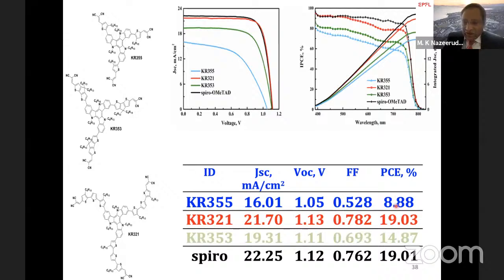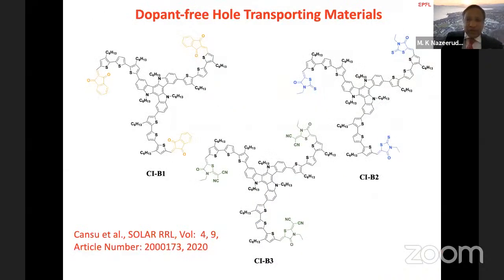With one thiophene, the efficiency is not very high. With two thiophenes, the efficiency without any dopants is around 15%. With three thiophenes, there's KR321, the red entry, with around 19% efficiency. This is a pristine molecule, synthesized and directly absorbed onto the surface. On the contrary, the spiro is with the dopants, and the efficiencies are comparable. So here we have a huge success in demonstrating dopant-free hole transport materials as efficient as the doped spiro-OMeTAD. Followed by that, we have made another new class of materials, which we published last year.